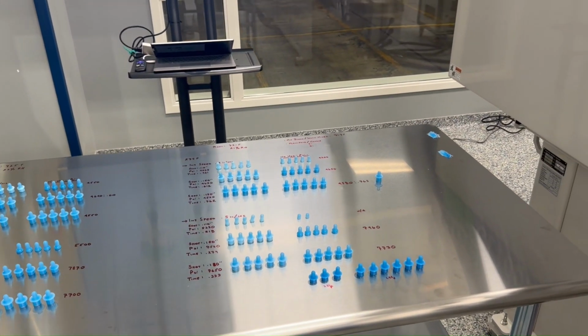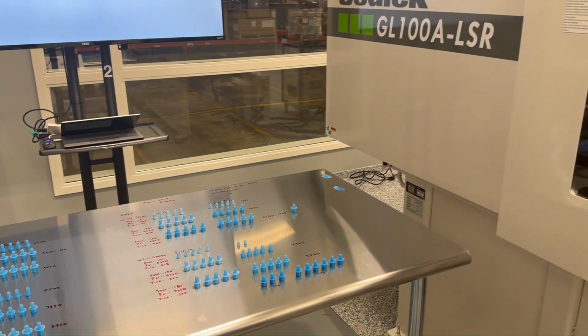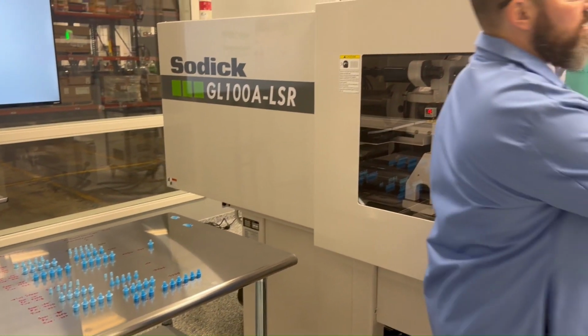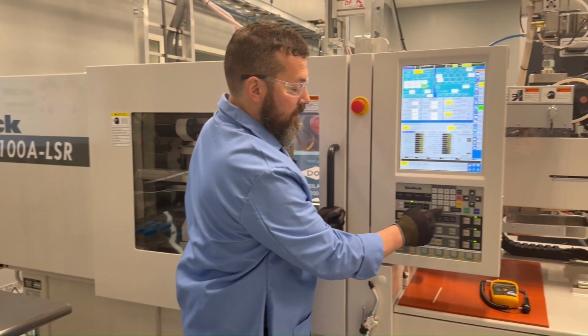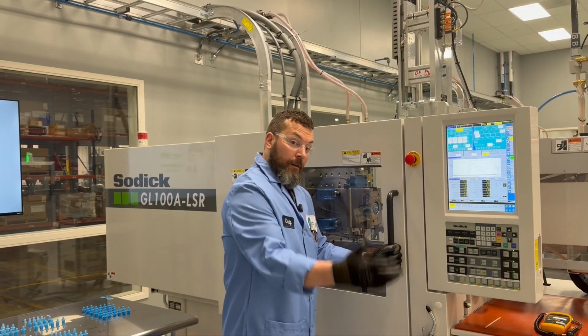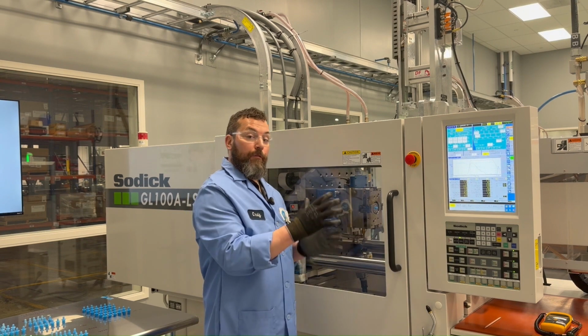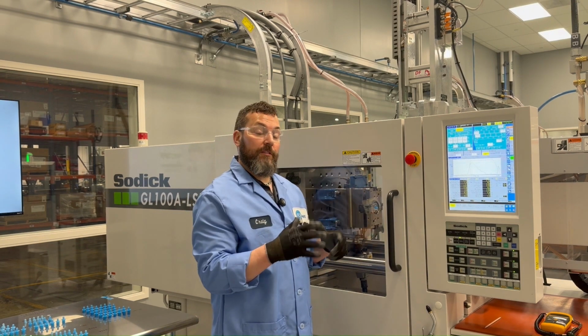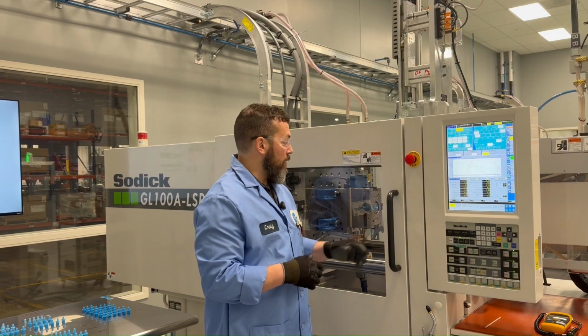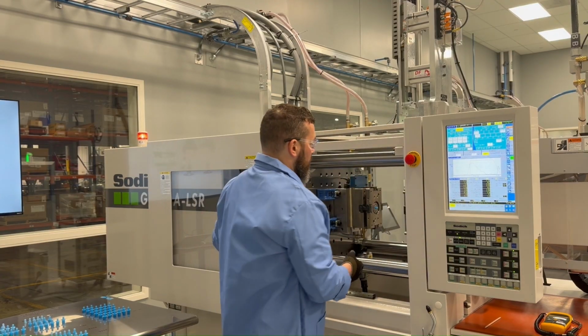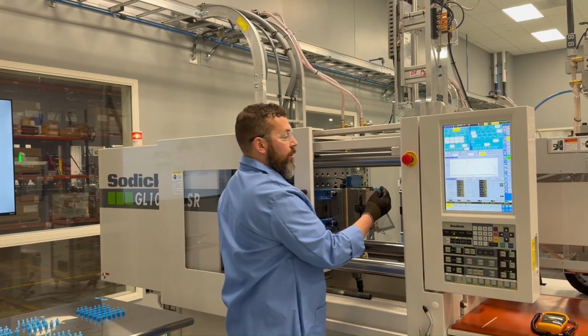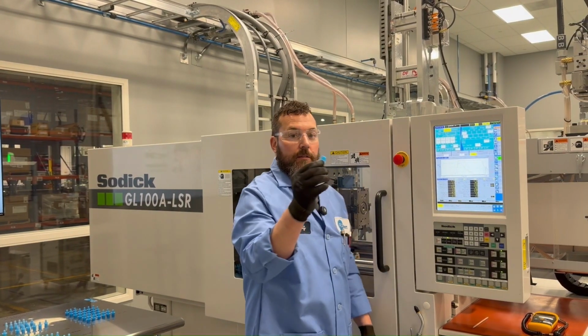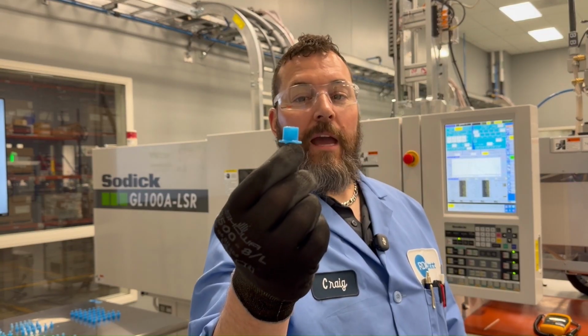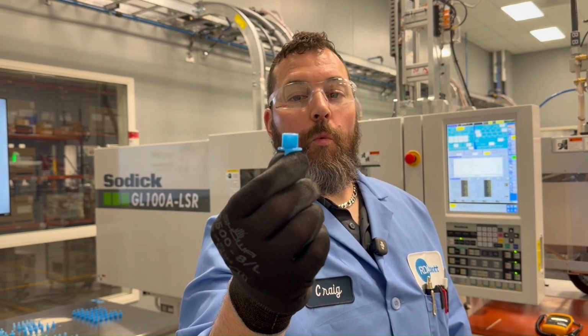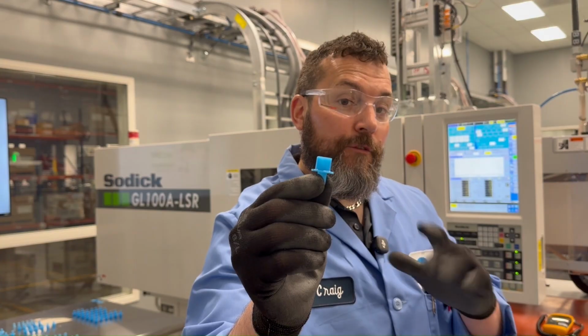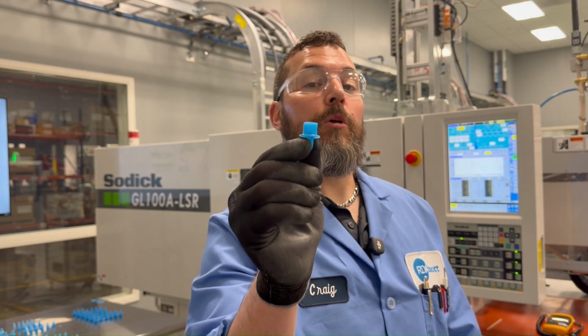So we'll increase it up a little bit more. So we went 500 PSI. Now what I'll do is I'll adjust this up to 1000 PSI. So we run some iterations without vacuum on just our hold profile to see how this part is filling out. Now, we weren't really worried about the hold time per se. We were just worried about the hold pressure. But with no vacuum, that white around the edge, and I'm not really filling that part. That is a burn blister.